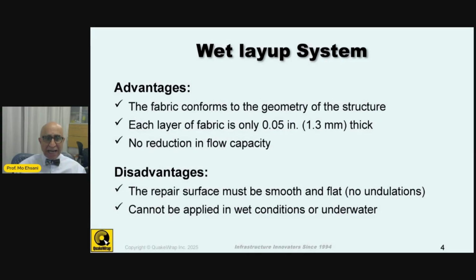The disadvantages of the wet layup system, a couple of main ones, are that you cannot apply that to a jagged or rough surface. The surface of the concrete, for example, is corroded. You must first repair that concrete, patch it, make it smooth, and then apply the fabric to it. And this is one of the shortcomings of it.